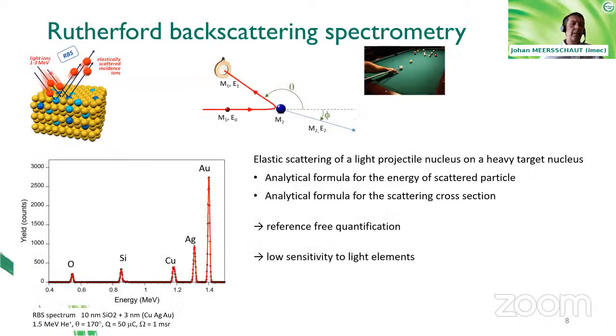So the basic idea already identified and recognized by Rutherford is that when light particles are impinging on a sample, then there is a small probability that this helium particle will be scattered on the nucleus in the sample. The probability of backscattering or scattering on the nucleus is extremely small, because the cross-section of the nucleus is very small compared to the total size of the atom. But if it happens, there will be a collision, an elastic collision between the positive charge of the incoming ion with the positive charge of the nucleus in the sample on which you scatter.